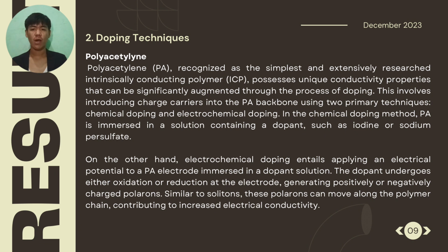First, polyacetylene is a well-researched ICP with unique conductivity properties that can be enhanced through chemical and electrochemical doping. In chemical doping, it involves immersing PA in a dopant solution, such as iodine, creating positively charged species, thereby improving electrical conductivity. Otherwise, electrochemical doping utilizes an electrical potential to induce oxidation or reduction, generating charged polarons that contribute to increased conductivity.